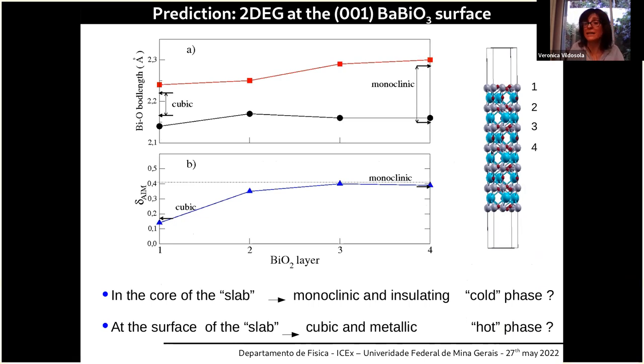Then we studied the evolution of the breathing distortions by checking the bond lengths of the bismuth 3+ layer by layer in the slab that we have simulated, and we observed that it was shrinking. Further away from the surface, the breathing distortions were very similar to the ones that the system has in bulk in the monoclinic situation, and these breathing distortions were sort of decreasing toward the subsurface and the surface layers. They don't reach the distortions that the system has in the cubic bulk phase, but they go in that direction.